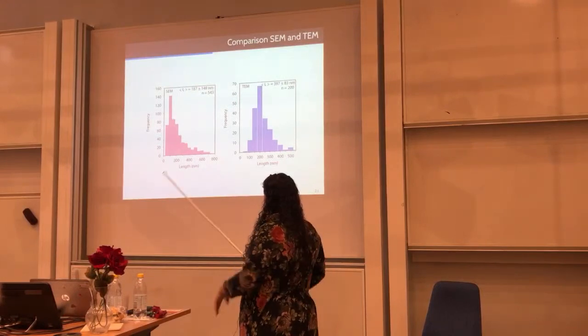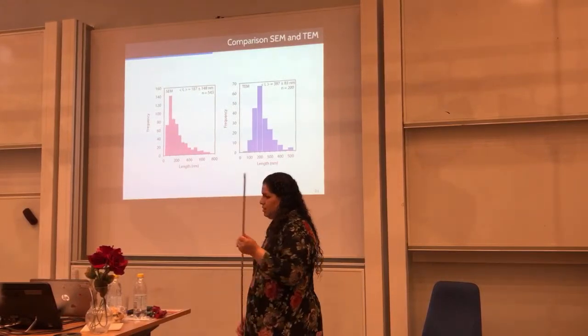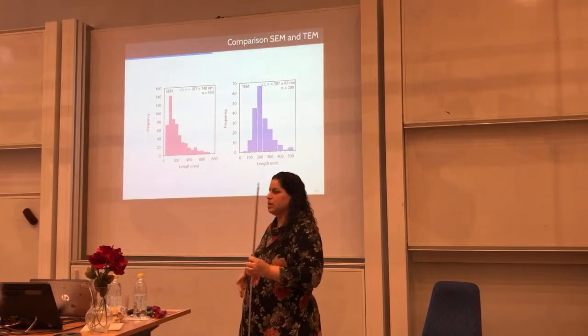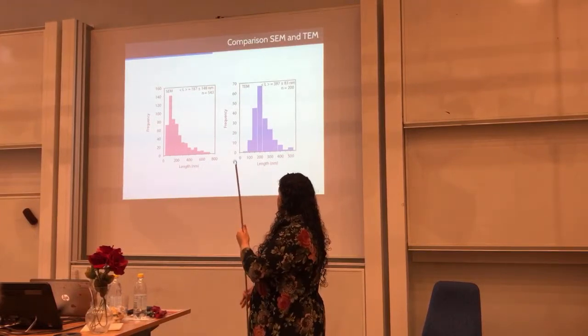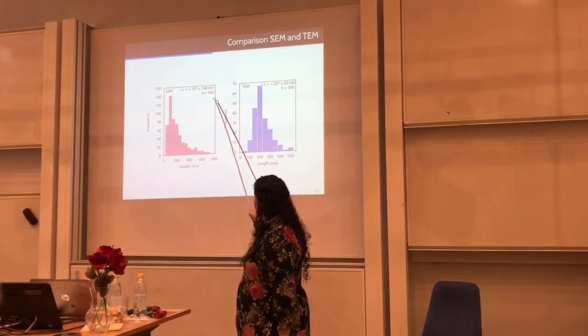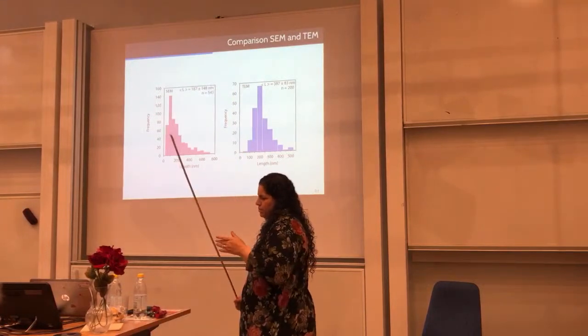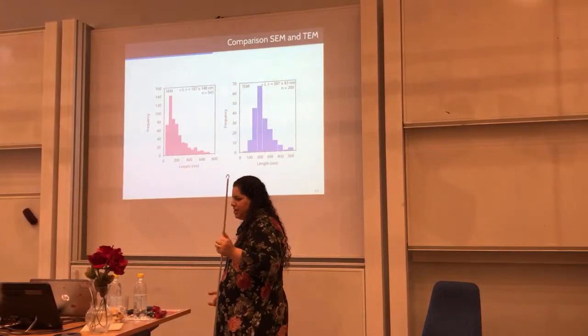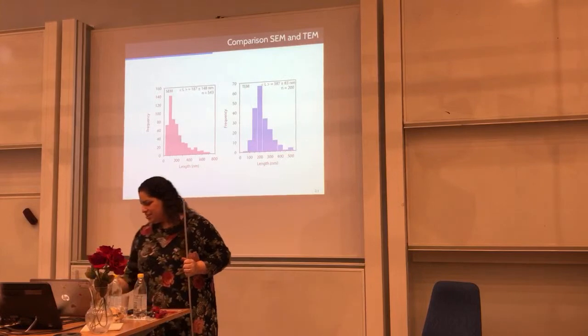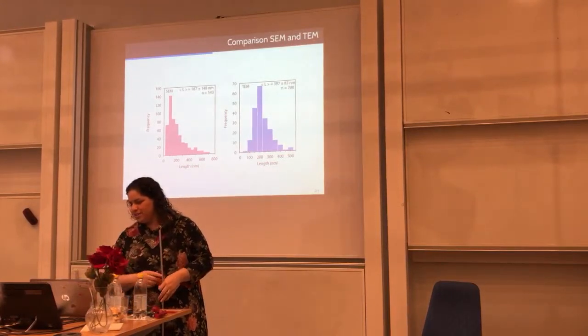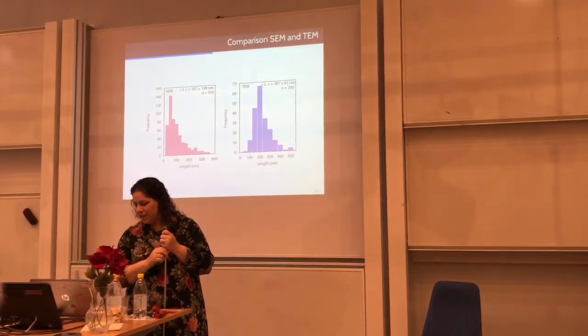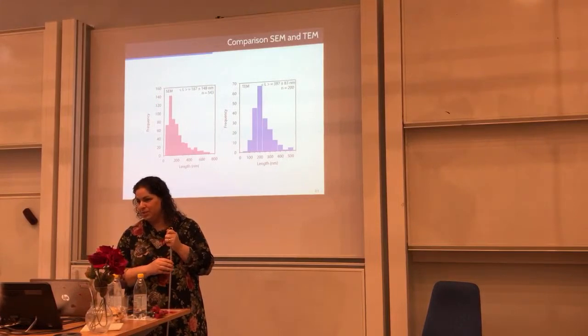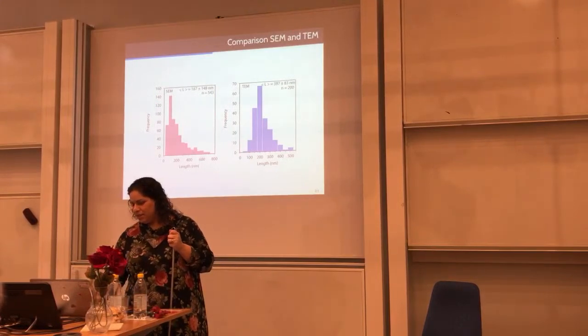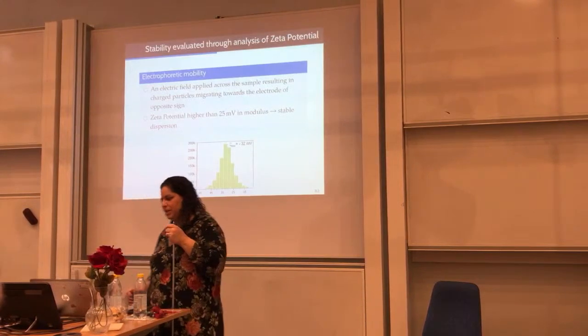But when you're using the SEM, we are not selecting a particle. We are measuring the whole surface. So you have a much larger number of particles, and that affects the result, and we end up having half the size of the particles. So it's not really right to say that SEM or TEM was better to measure this, but the way we measure it was different. You measure more particles in one technique.